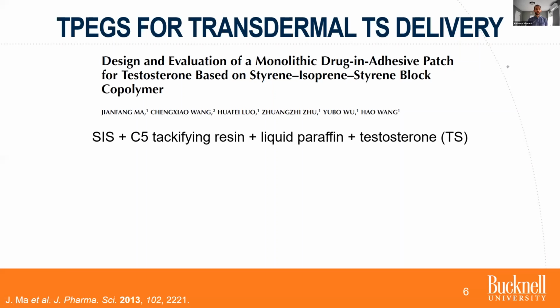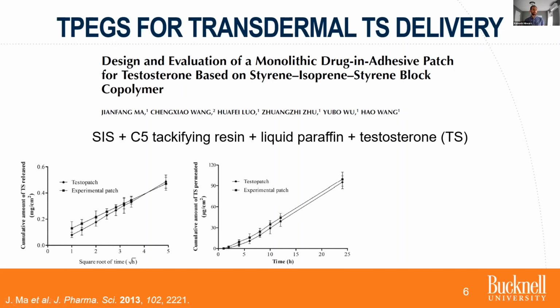for transdermal drug delivery. And what this paper did is it combined classic kind of thermoplastic elastomer, which is styrene, isoprene styrene, shown by SIS here, along with a tackifying resin to increase adhesive performance, liquid paraffin, and their kind of probe molecule or probe drug, which was testosterone. And this study does a number of different things from a statistical standpoint. It's actually done by a pharmaceutical science department group, and so a lot of it's focused on the application of these materials. But basically the main findings from their study are that in vitro, the release of testosterone with time and the amount of testosterone permeated through, in this case, pig's ear skin, are very similar to an on-the-market testosterone delivery patch, which is called Testo patch.